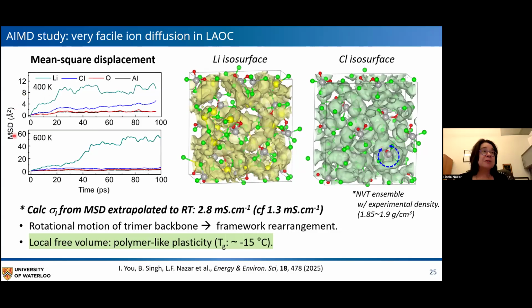This is borne out in the MSD, both at 400 and 600. And you can also see that at 400, there's even some mobility of the chlorine, but this is not translational mobility. This is actually the oligomer sort of flopping around, as best one can say, in this environment. And this, we believe, this rotational motion of the trimer is what gives rise to its plasticity, at a glass transition temperature of about -15.